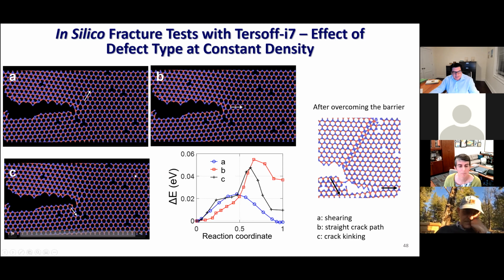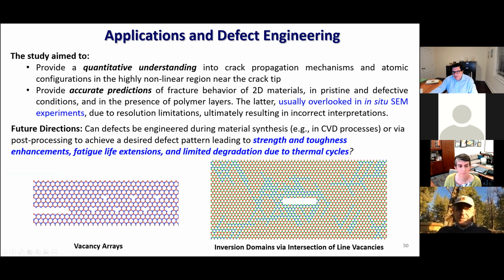But everything makes sense, and I think your observation that you think of this as a lattice with the weakening, but some people found on graphene, in the case of graphene, some significant toughening. But we don't see that here, and most likely it is because of the different chemical environment and properties. We still are investigating more complex scenarios of grain boundaries generated by line of vacancies, and that may be more promising. We don't know yet.